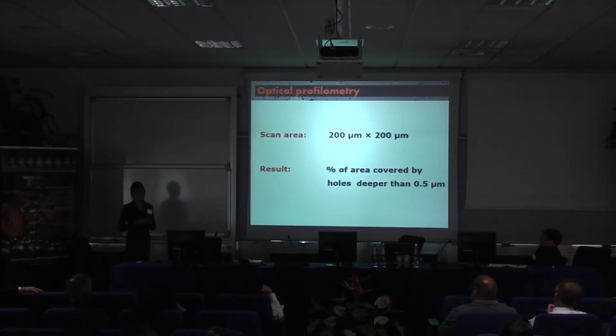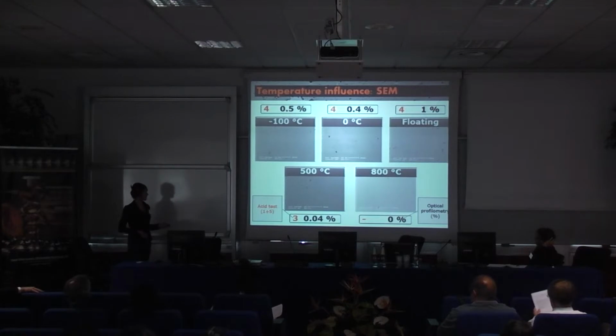We have compared the results that we have obtained on acid test of porosity with the direct measurements of porosity like optical profilometry and the scanning electron microscopy. The result of optical profilometry is the percentage of area covered by holes deeper than 0.5 micron. Here you can see the temperatures of deposition. In orange color you see the results of acid test, and in black one you see the optical profilometry results.